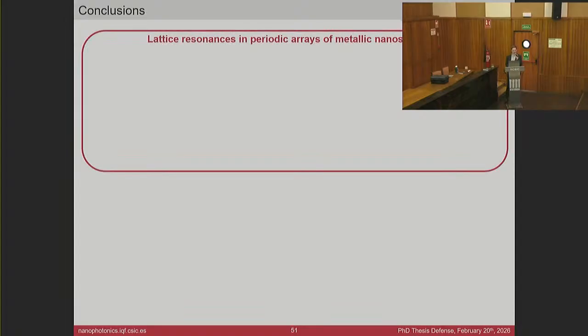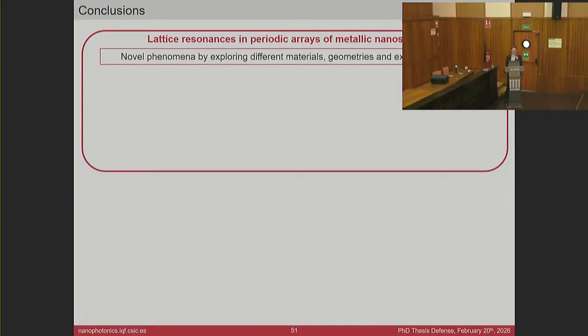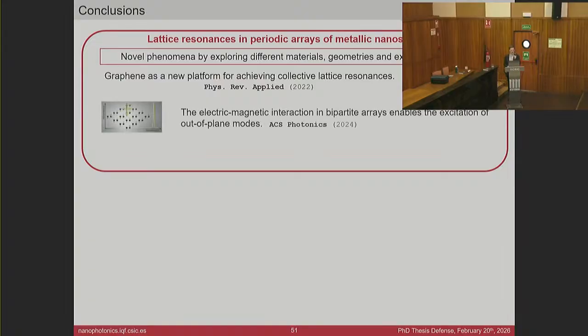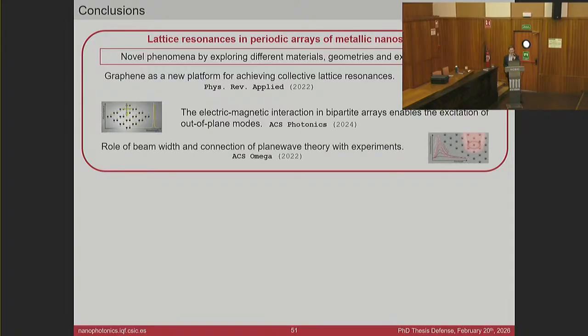Now, this finishes the results. I'm going to give some conclusions. We have studied lattice resonances in periodic arrays of metallic nanostructures. We have explored new configurations, and in particular, a new material, graphene, as a platform for achieving collective lattice resonances. We have explored new configurations of the unit cell to sustain excitation of out-of-plane lattice resonances at normal incidence. And we have unveiled the role of the electric-magnetic interaction, which is many times neglected in systems of metallic nanostructures, and which is really important in the case of collective modes, as we have seen. Finally, we have ascertained the role of the excitation source to excite these resonances, and we have bridged a gap that was missing between plane wave theoretical studies and experiments.